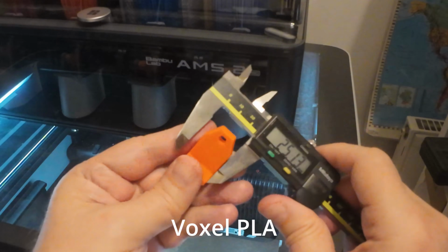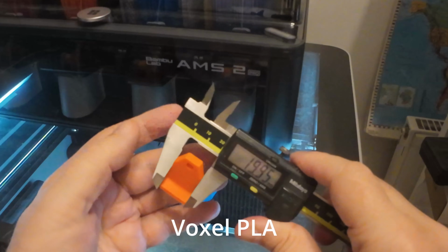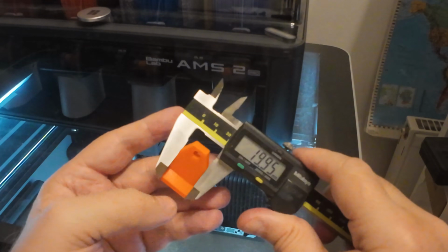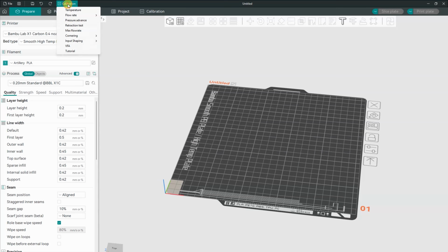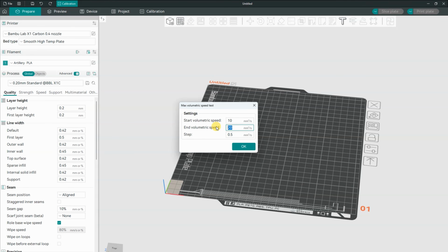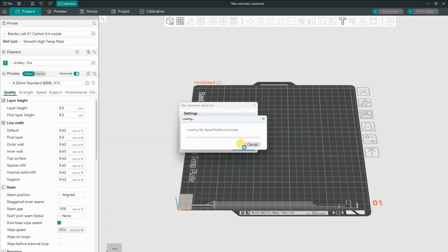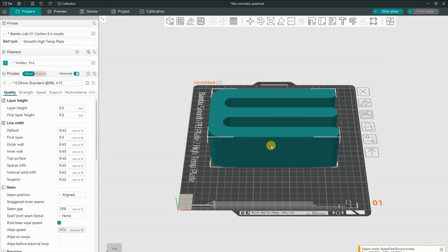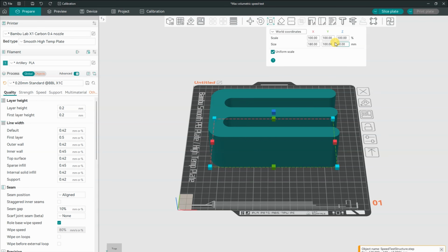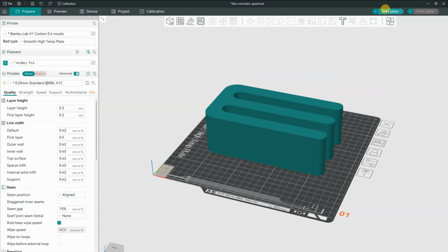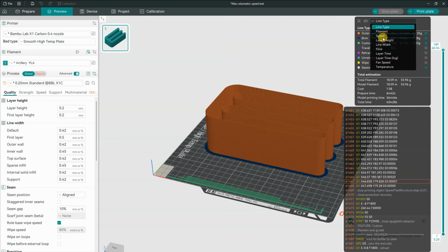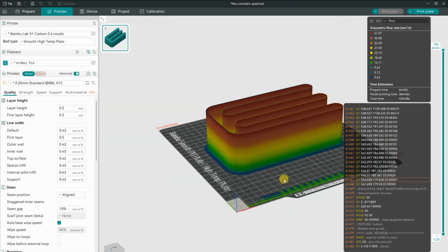19.97, 19.95. Let's measure that ultra high flow. I'm preparing the test from 10 to 40 cubic millimeters per second, and using this step the object will be exactly 60 millimeters. With this it's easier to calculate the flow from the height. And here you can see the preview switching to the flow from 10 to 40.